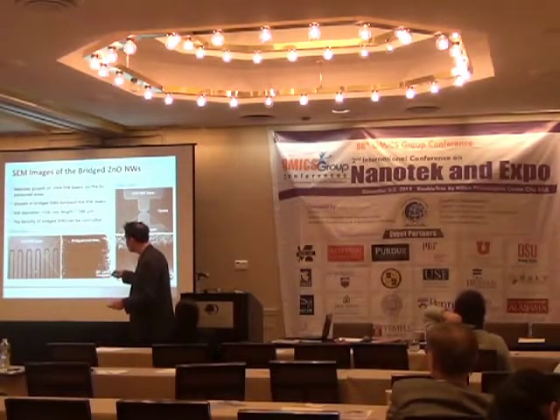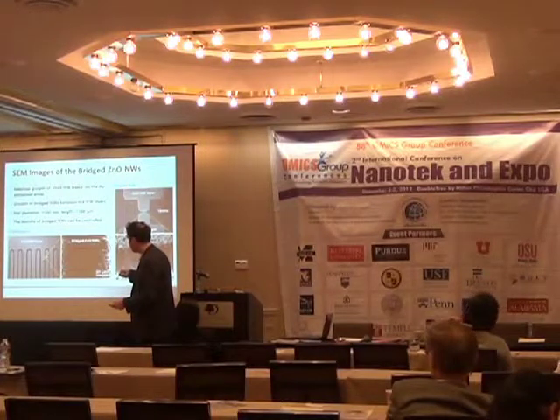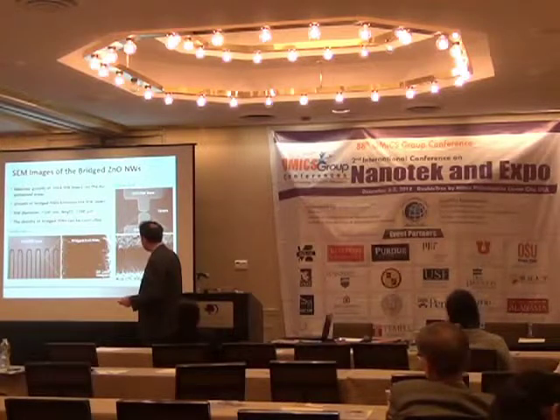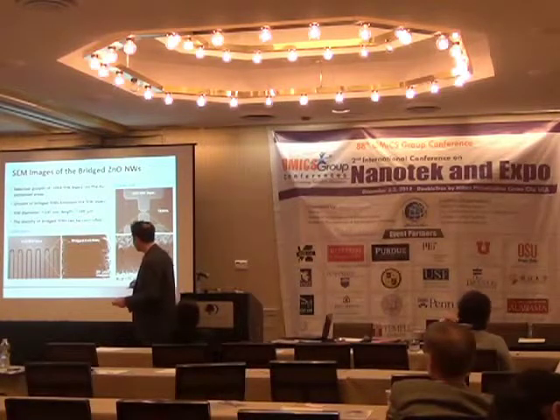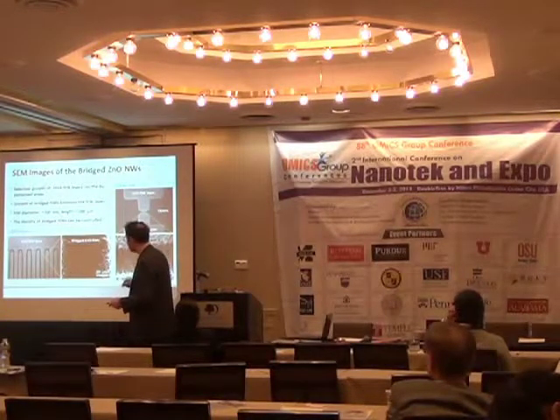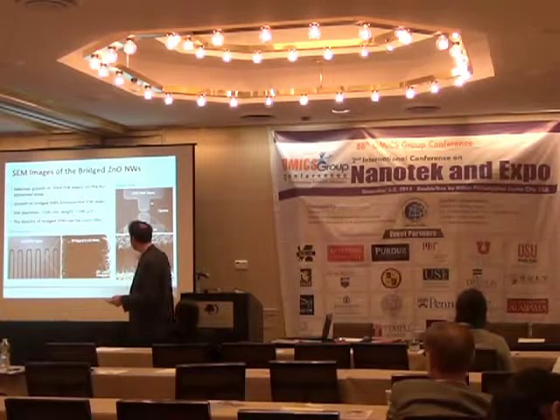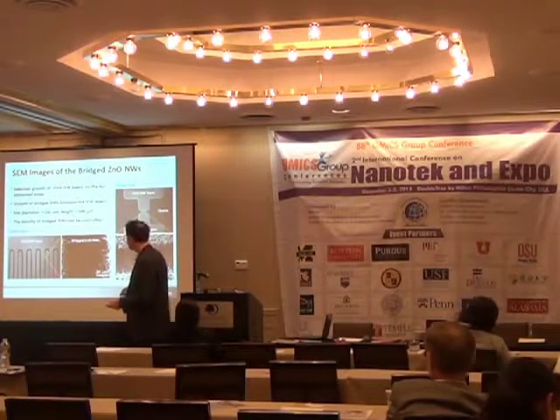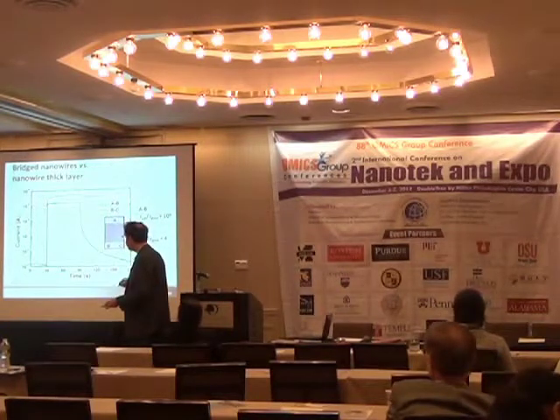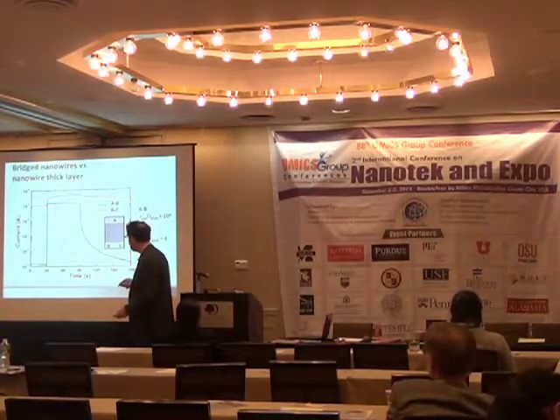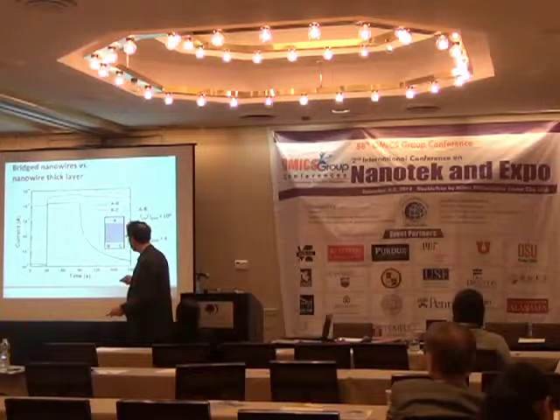Good. So these are the results. That's for the cone structure here. In dark here, what you see is a gap. If you zoom in here, you see some bridges like that. And this is a finger structure. Again, in the gap here, you have nanowires connecting the two electrodes. Cones are very nice to make large surface detectors. These are for array detectors. Good. So this is the main result that shows you that it works quite well.